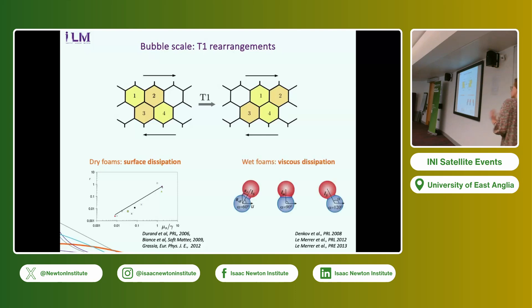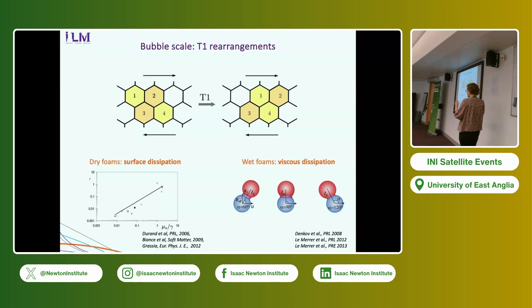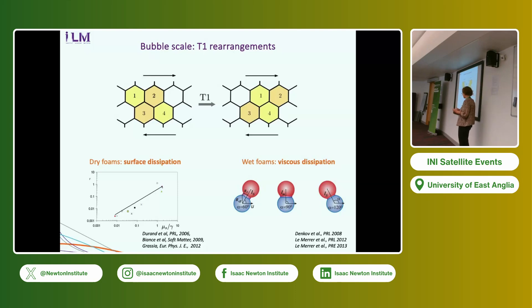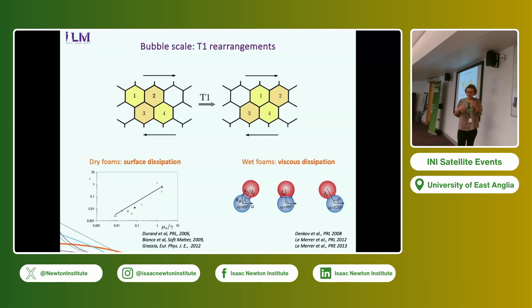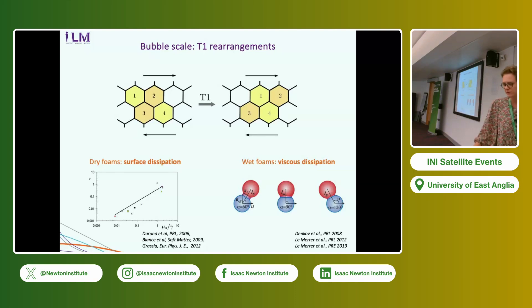From a mechanical point of view, this timescale is correlated to what we call the surface viscosity μ_s divided by the surface tension — a characteristic time scale of the T1 rearrangement dynamics. In wet foam experiments it was also shown to depend on the liquid viscosity, giving a balance between interfacial properties and bulk properties.